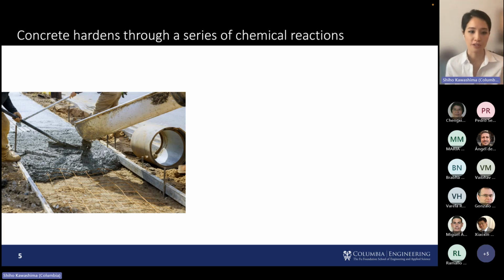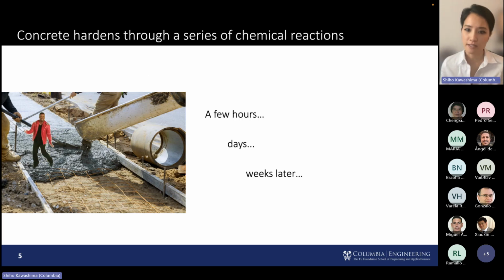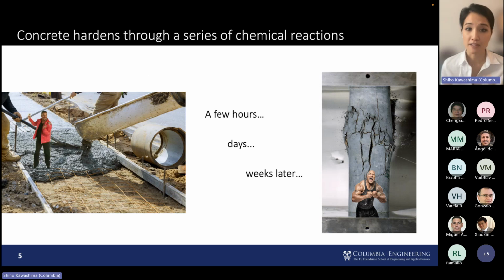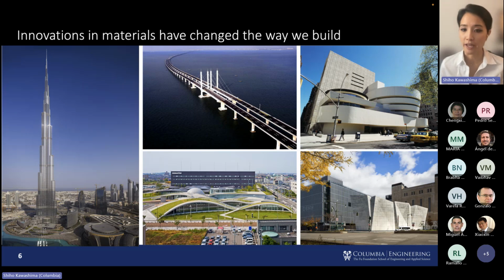And so as a result of that, it undergoes various phase changes, really incredible, starting as a fluid, flowable material. So it really moves during construction, but then a few hours, days, and weeks later, it turns into this rock hard material. And this is because of these series of chemical reactions, right? And so I think a number of us who are speaking today, and maybe some of you in the audience, you know, concrete is typically thought of while it's in the hardened state, which is of course important, but the fresh state, even though relatively it's a short period of time, is really important because it will determine the eventual performance of the structure in place, but it also will govern how efficiently, how well construction goes. So it really has a significant impact on constructability. And that's really changed the way we build today.